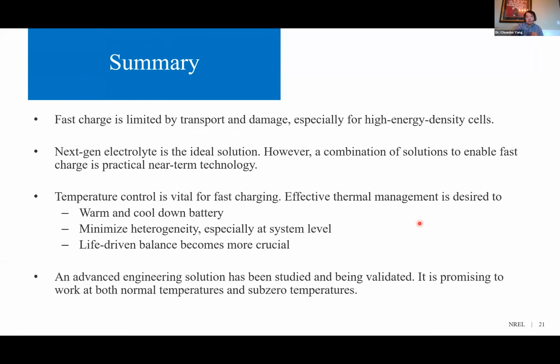With that, please let me give you a summary of what I have been talking about over the last hour. First, we talked about how fast charging is limited by transport and damage, especially for high energy density cells. Ideally, next generation electrolytes with higher conductivity, diffusivity, and transference number will be available. A combination of solutions is probably a practical solution to enable fast charge.